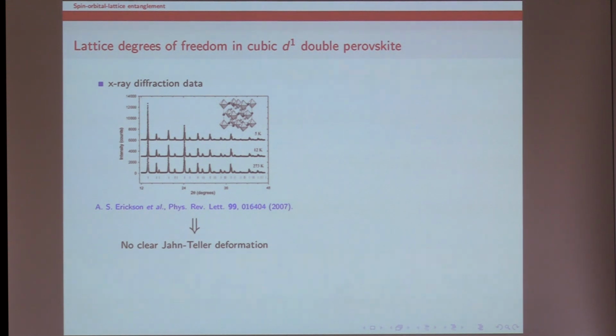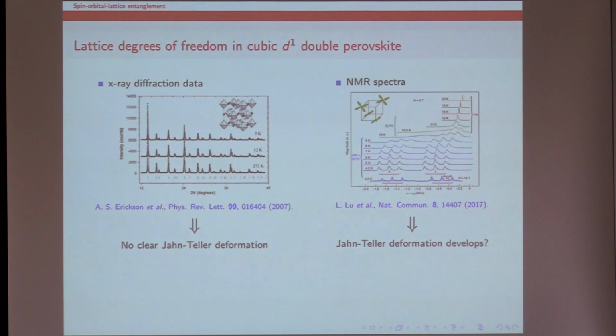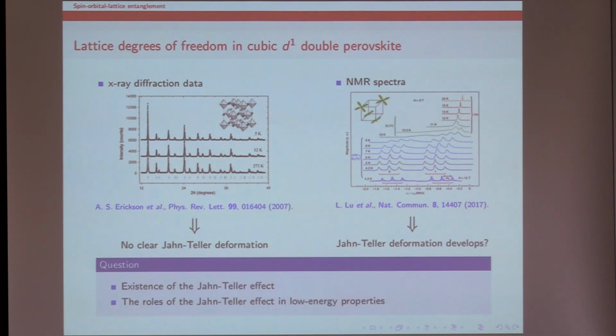And regarding lattice degrees of freedom, there are a couple of questions. First of all, X-ray diffraction shows no clear Jahn-Teller deformation or symmetry lowering down to low temperature. On the other hand, a recent NMR experiment shows a sign of development of Jahn-Teller deformation. So our questions are whether the Jahn-Teller effect exists in this material or not. And then if it does, what is the role of this effect in low energy properties?